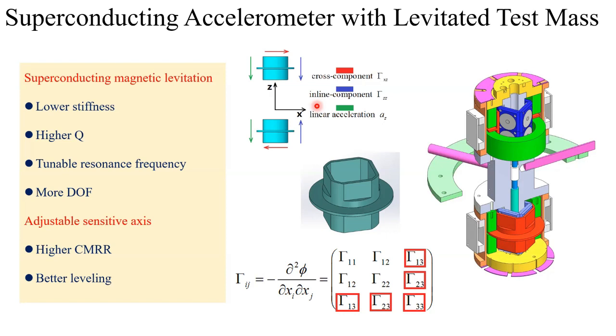The second one is there is no spring, so there is no deformation of material and no internal friction. So the quality factor can be very high, and this lowers the thermal noise. The third one is tunable resonance frequency. Because the test mass is levitated by a magnetic field, we can adjust the current in the levitation coils to increase or decrease its resonance frequency and match the two test masses inside the detector.